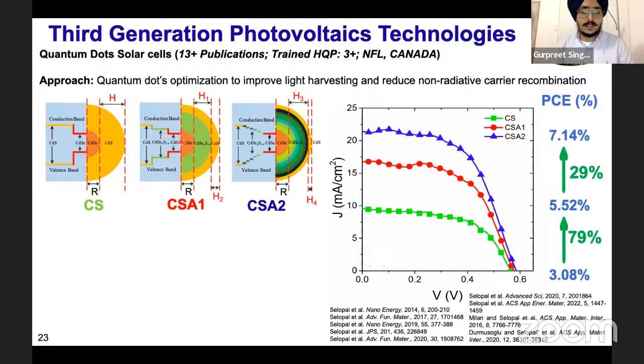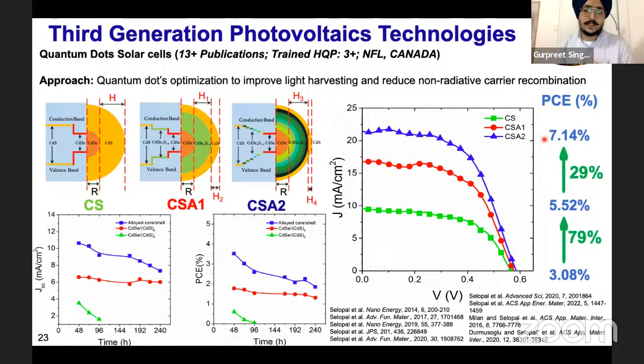And when we engineer the interface of the core-shell quantum dot, we improve further. As you can see, by engineering the interface of the core and shell material, we significantly improve our efficiency from 3 to 5 and 5 to 7. And recently we obtained a new record in the power conversion efficiency. In addition, we also obtain pretty decent long-term stability for these types of quantum dot solar cells. But still we are struggling to further improve the power conversion efficiency as well as the long-term stability.